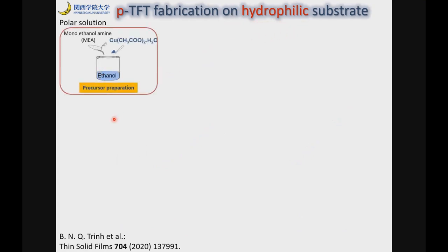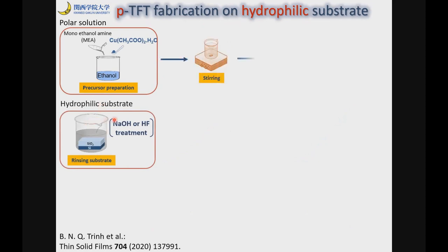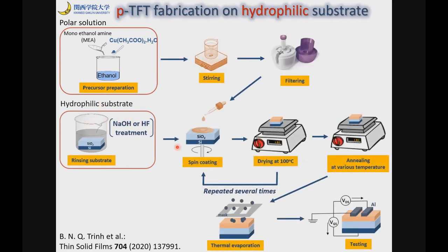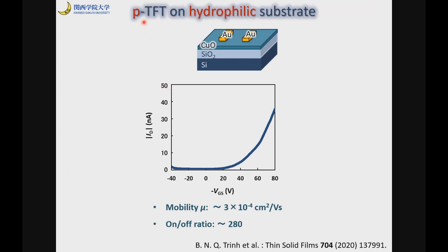Okay. So the next trial was the P-type TFT fabrication on hydrophilic substrate. This time also the materials are different, but our processes are the same. Looks like this. We also succeeded in fabricating the P-type TFT on hydrophilic substrate. In this case, a copper oxide layer with the gold electrode. So the mobility and the on-off ratio are not so high, and now my student is trying to improve both. But so far we succeeded in fabricating P-type and N-type TFTs by solution processing. This is a very important achievement.